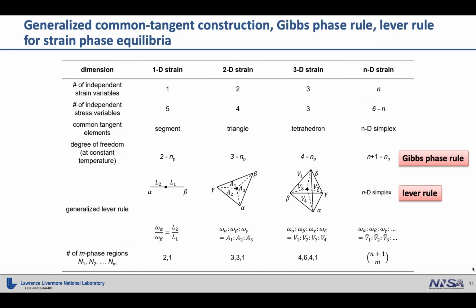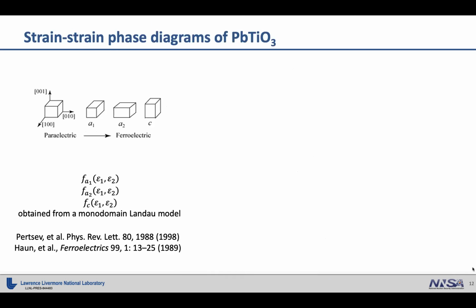And we can generalize the Gibbs phase rule, the lever rule, and the common tangent constructions from 1D to 6D strain space. The Gibbs phase rule tells us, in each phase region, what's the maximum number of phases that can exist in that region. And the common tangent and the lever rule give us a quantitative estimation, for a given total strain state, of what the volume fractions are for different local strain phases. And this is all good, but they're all just intuition and schematics. We apply this theory, which we call strain phase equilibrium, to some real materials.